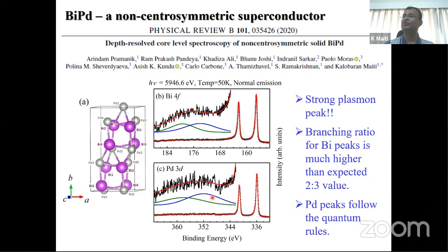So first, I'll show you some of the core level spectrum, which has a lot of implication in the band structure. That's the reason I'm showing it first. And then I'll give you an introduction about the band structure of this material without talking much, because we don't have much time in this talk. If you look at the core level spectrum, this is the crystal structure, which you might have noticed, and the core level spectrum shows bismuth 4f and palladium 3d. It shows a lot of loss features due to plasmon, but the main interesting thing is that it has sharp spin orbit split palladium 3d peaks and bismuth 4f peaks. So let's focus on these two, which are very sharp.